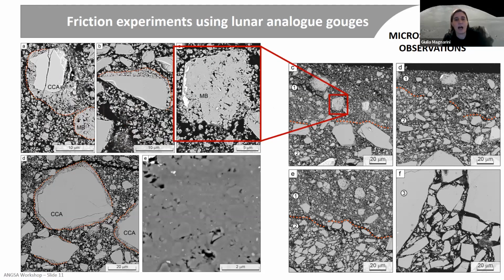And so we can look at this clast fabric in a bit more detail. So MB stands for melt ball, which is here inside the red box. And below it, we have a zoom in into this melt ball. So melt balls are clast aggregates with solidified melt. Whereas the CCA, clast cortex aggregates, are made of a central cluster surrounded by fine-grained fragments that derive from the breaking of the cluster itself.